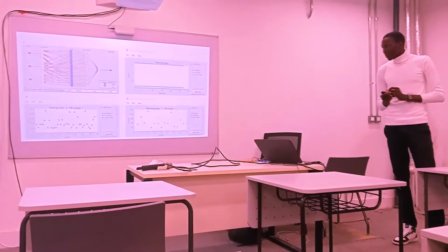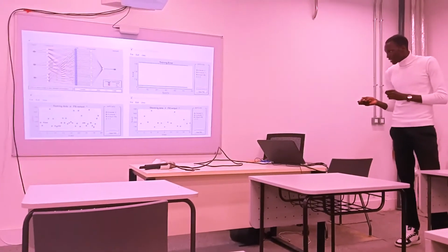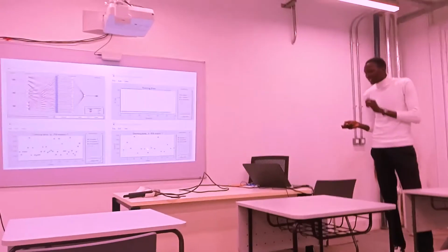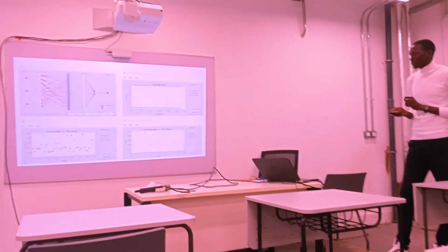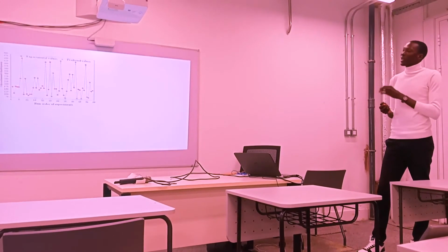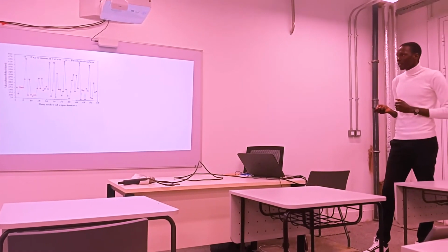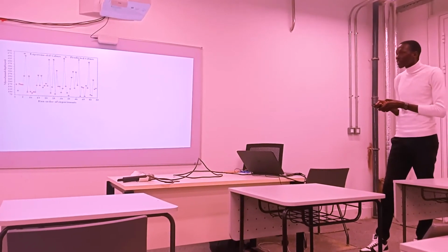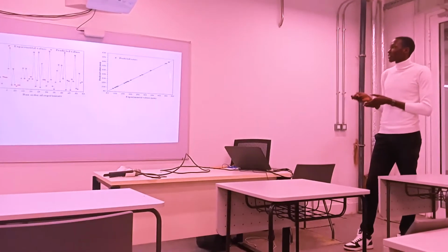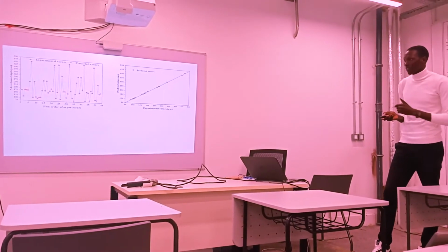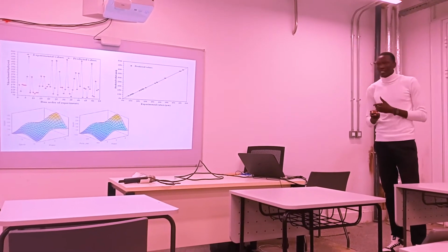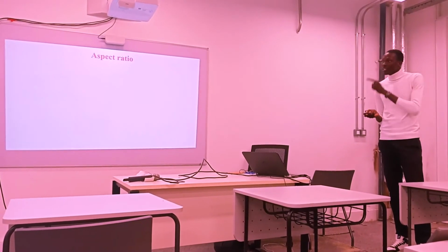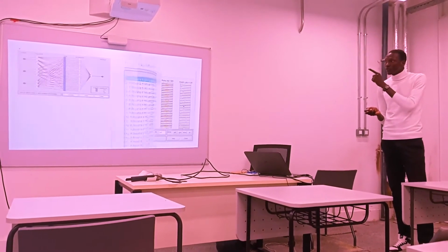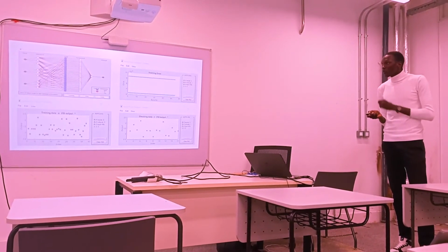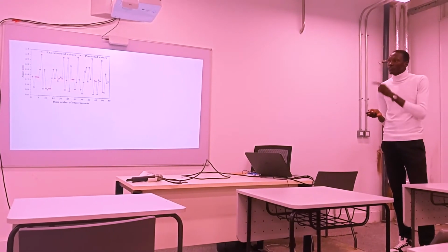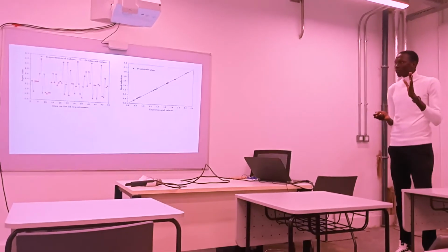For the 30% of the data used for checking, this graph compares the values of the 30% data and the predicted values. We compare the experimental values and the predicted values again. Again, we see that the values are very similar. They are so close, and a similar graph to what we got for width. Again, showing high accuracy of the model for depth. We did the same thing for aspect ratio. And we were able to also compare the predicted values and the experimental values, similar to what we did for depth and width.